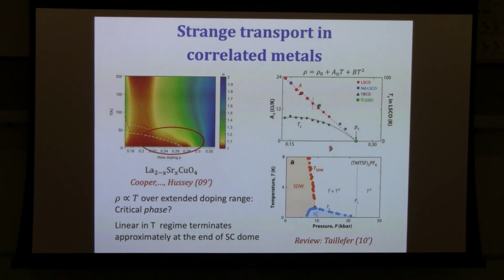And in all these systems, the empirical observation is that you can fit the resistivity as a function of temperature to this simple form: some coefficient A times T plus B times T squared. And the observation in this article is that in both of these systems, the coefficient of the T squared term is more or less tuning parameter independent, or weakly dependent on either doping or pressure. But the coefficient of the linear in T term seems to vanish.